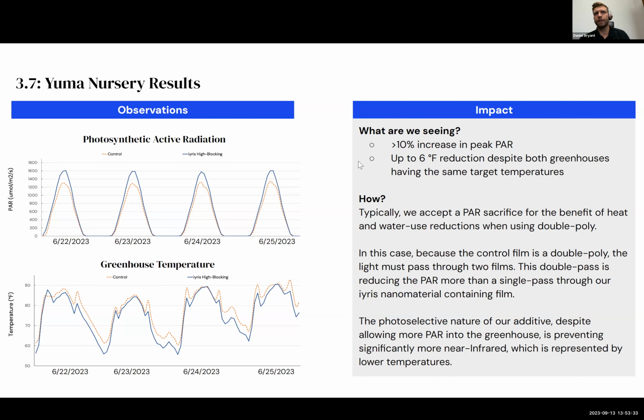I mean, the roof, in terms of mechanical properties, even a polyethylene roof could stay good for 8 years, but it's just milky, and it's cost effective to replace it. Some of these guys are replacing once every year, like every season, but usually 2 to 3 years is when you replace. So we don't have an impact, and as I say, always worth bearing in mind, we're actually a very, very low concentration, because we're an optical effect. And that was one of the beauties of this material. We're not talking about having to put too much in to change just optical.